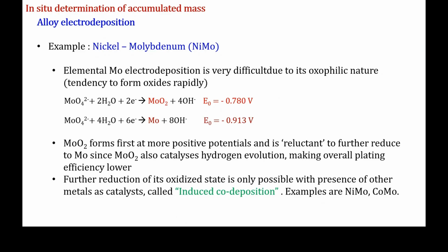So this requires essentially sacrificing an EQCM quartz crystal, paired with an applied potential from solution. So you coat the electrode with one potential, you measure the current, and you then measure the mass change, and you then see the composition of the electrode, which is going to be part nickel, part molybdenum.